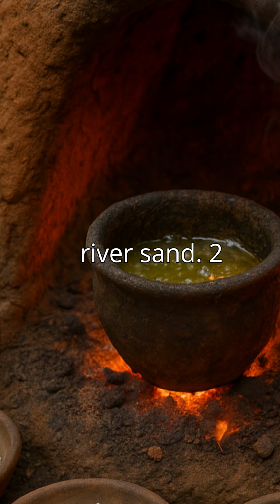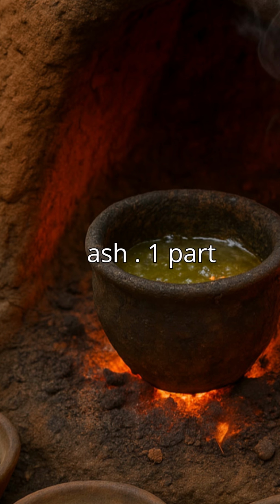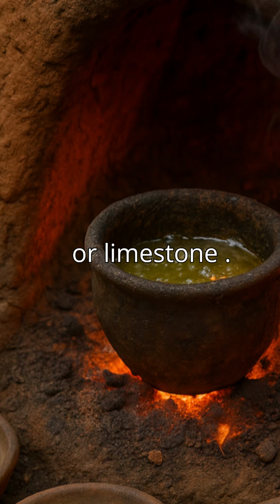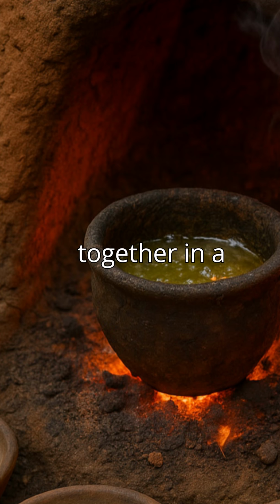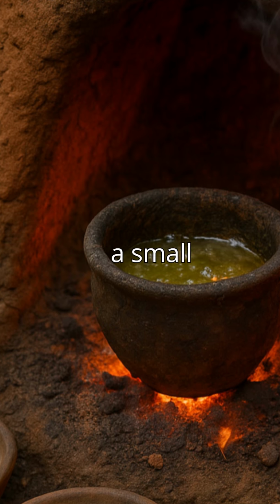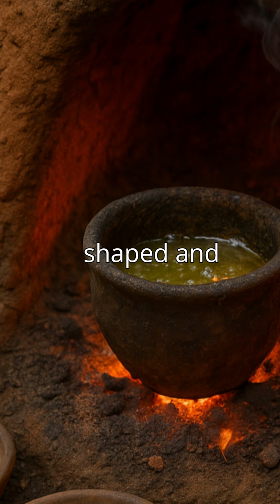He carefully measured out his ingredients. About 7 parts river sand. 2 parts plant ash, for soda. 1 part crushed shell or limestone, for lime. He mixed them together in a clay bowl, then placed the mixture in a small crucible, another clay vessel he'd shaped and fired in his kiln.